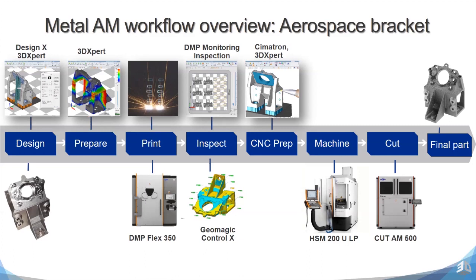So we were able to use our monitoring, which is the vision and the melt pool, and the inspection to make sure that there was no lack of fusion or porosity issues in this part. In addition, after the part was done, we were able to use our GeoMagic Control X and scan the part in and put a color map over the original CAD data to see what kind of variations may be present there.